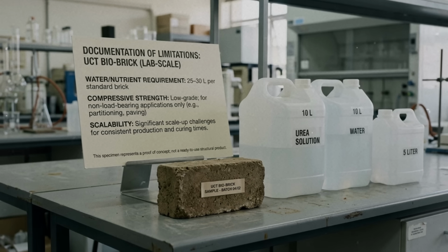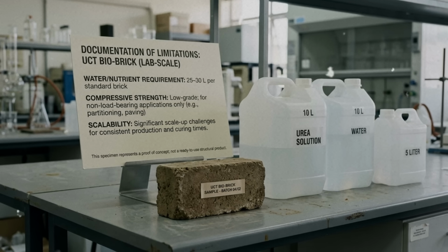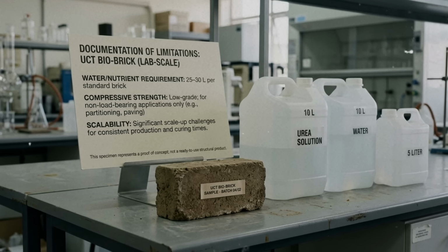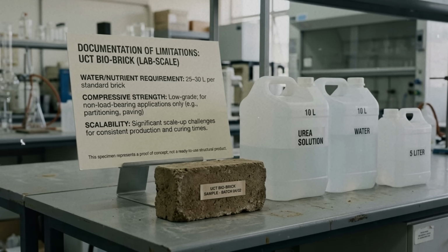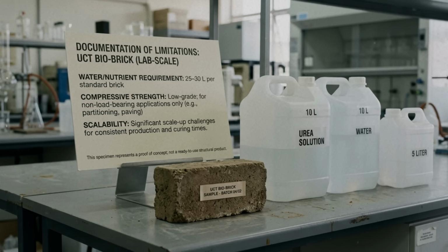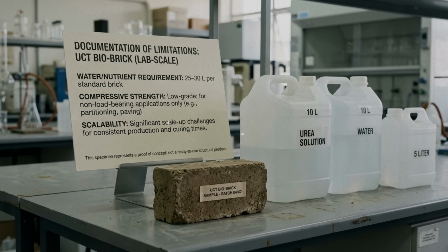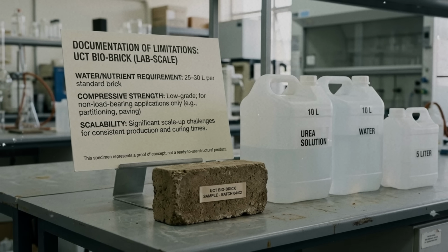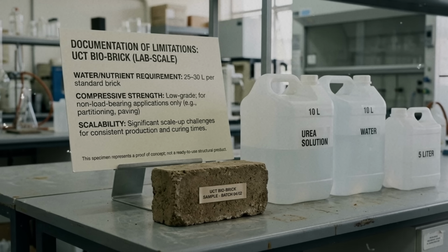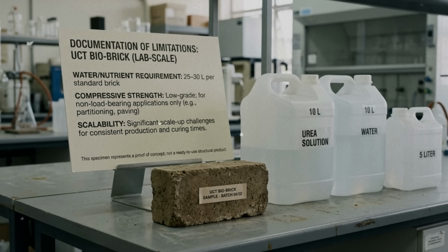It is important to be honest about the limitations at this stage. The UCT biobricks were a proof of concept. They required approximately 25 to 30 liters of urine per brick. The strength was comparable to low-grade masonry units, suitable for non-load-bearing applications, but not yet competitive with high-strength construction bricks. The researchers themselves acknowledged that the major challenge ahead was scaling up urine collection and optimizing the process for cost-effective production.